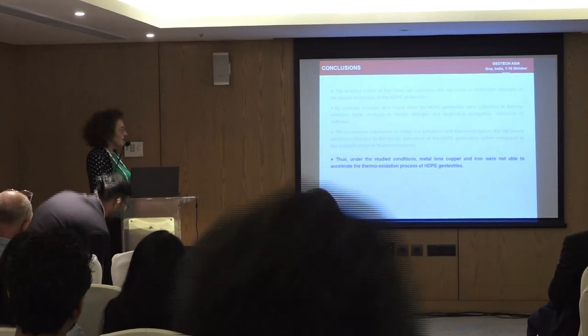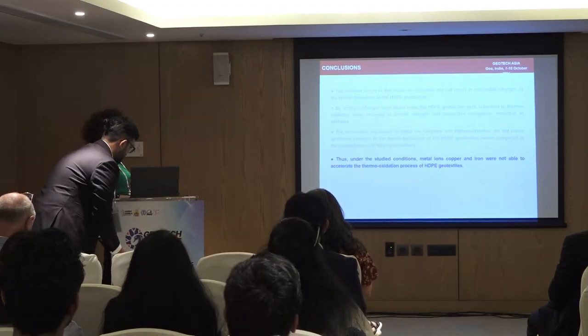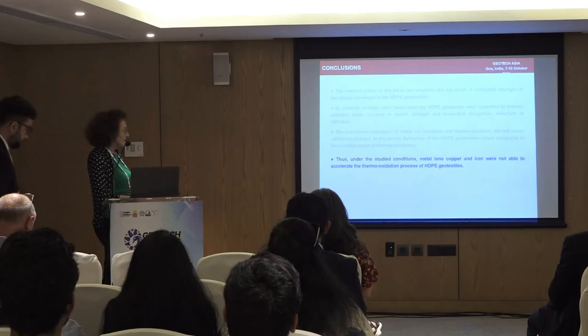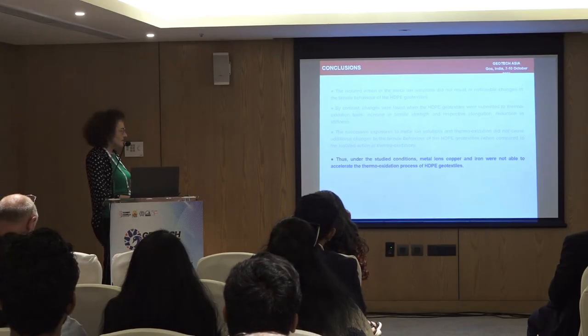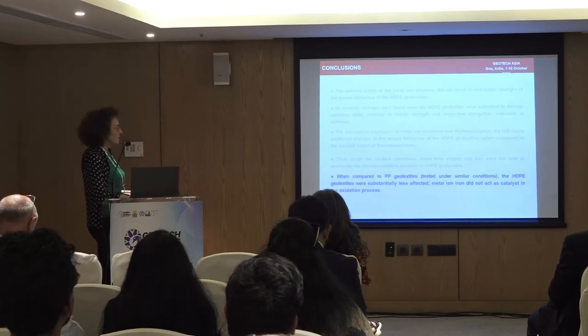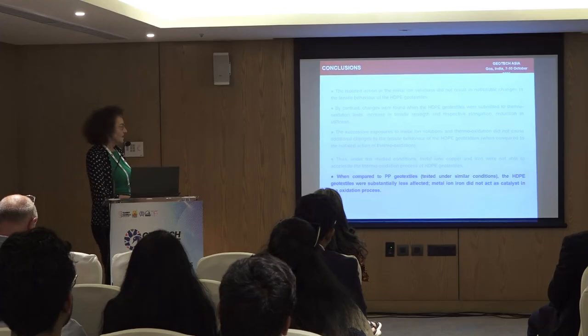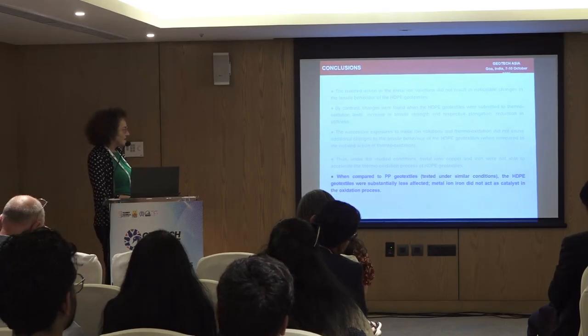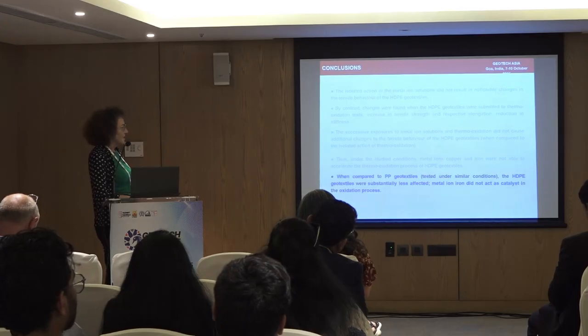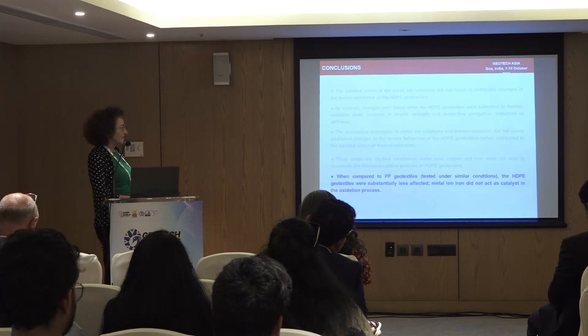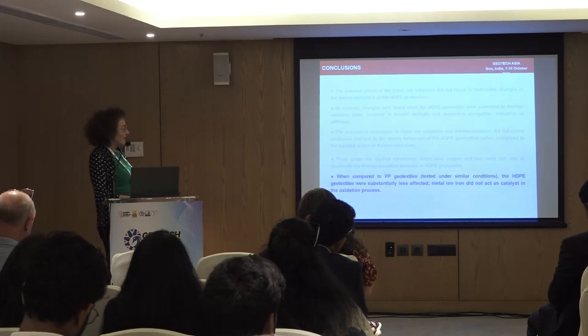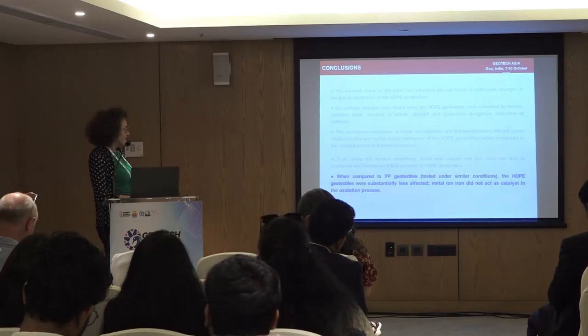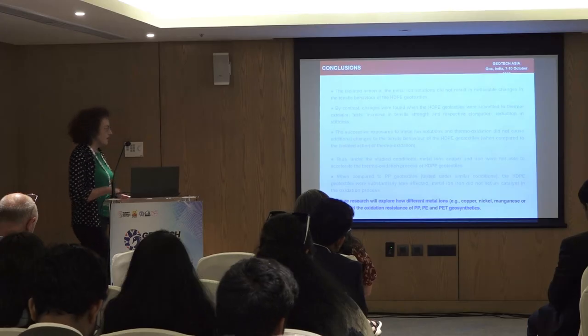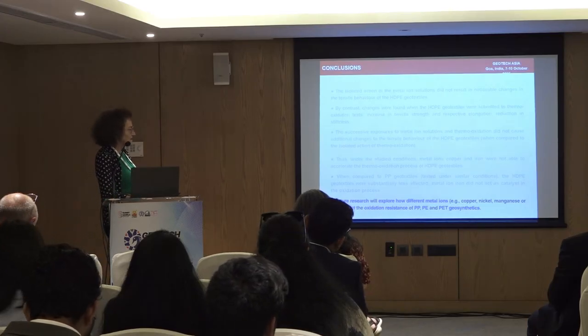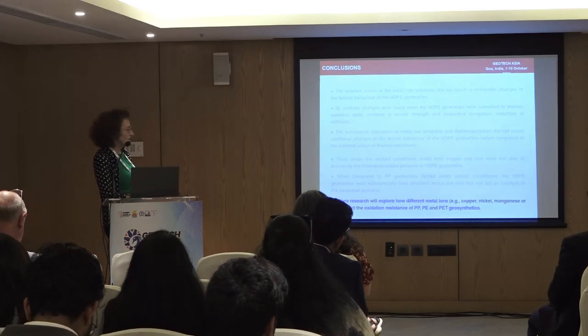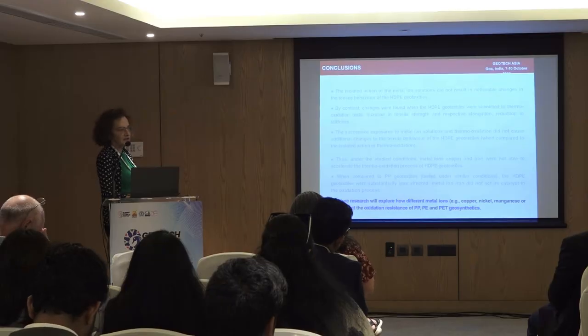So under the studied conditions, metal ions of copper and iron don't accelerate the thermo-oxidation process of HDPE geotextiles. When compared to the PP geotextiles that were tested in similar conditions, the HDPE geotextiles were much less affected by the action of metal ions in the oxidation process. Future research will explore how different metal ions, copper, nickel, manganese, and zinc, affect the oxidation resistance of PP, PE and PET geosynthetics.